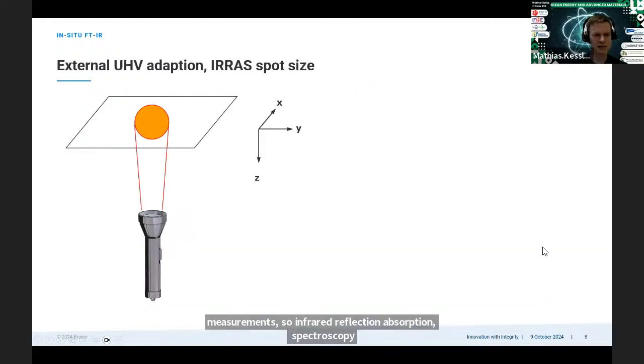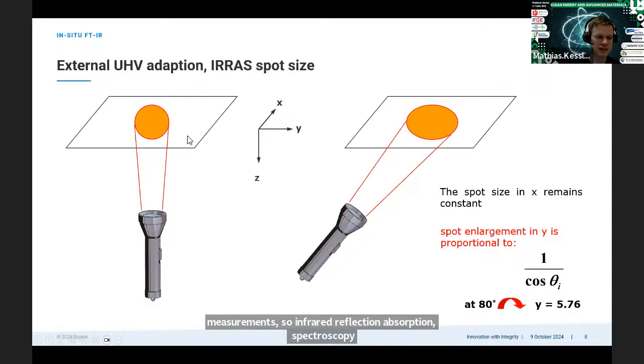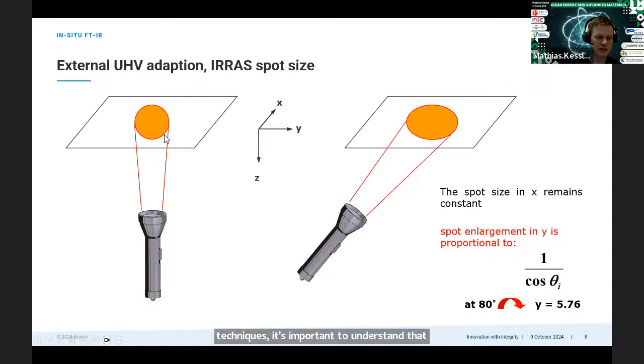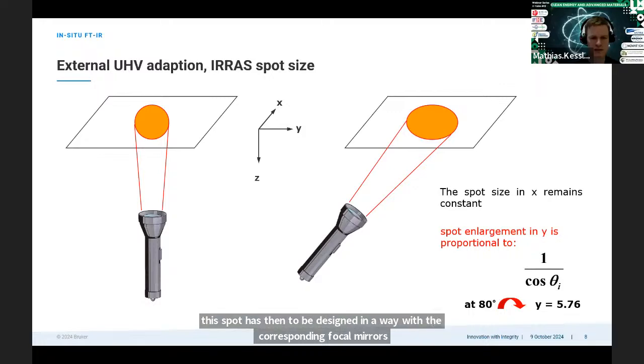For these kinds of techniques, it's important to understand that if we have not a perpendicular incidence of our light to the sample, but instead a certain angle of incidence, then of course the measurement spot is elongated in one axis, and this depends on the angle which is used. For example, for 80° of incidence, we have an elongation with a factor of 6 for the y-axis in this case. So we have an elliptical measurement spot. And of course, this spot has to be designed in a way with the corresponding focal mirrors to really cover the sample size of interest.